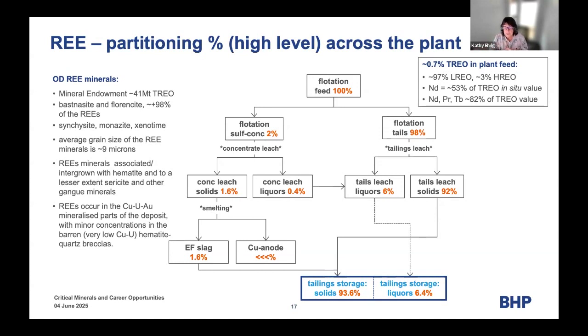When we do a concentrate leach in order to strip a little uranium out, but then we also take a little bit of copper, that we can see in the cons leach solids, the material that's going to be the feed into the smelter has 1.6% of our total rare earth stream. There's a little bit of rare earths in that leach liquor because we've dissolved the uranium minerals out. That goes back over to tails leach.